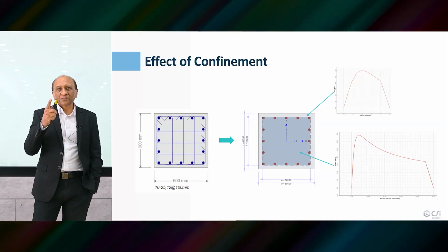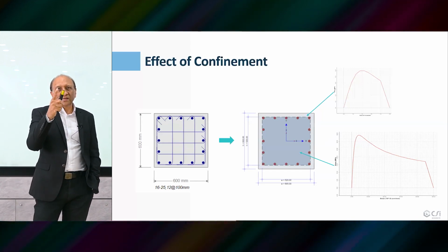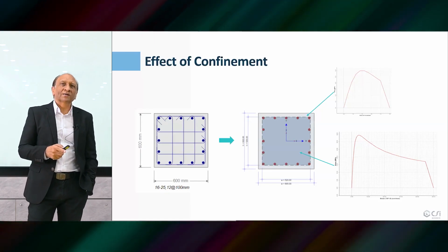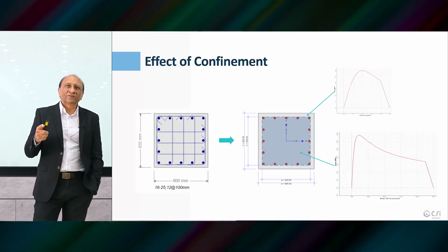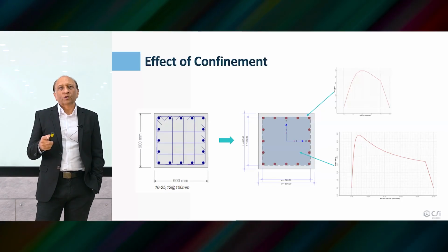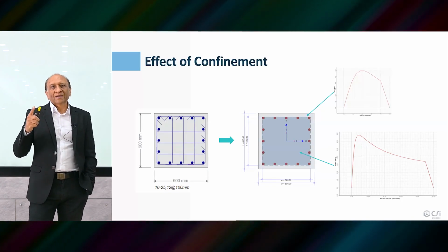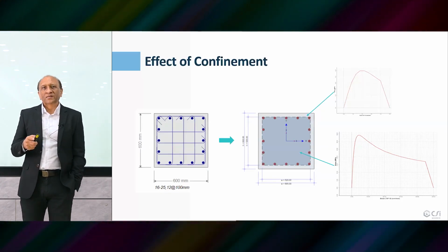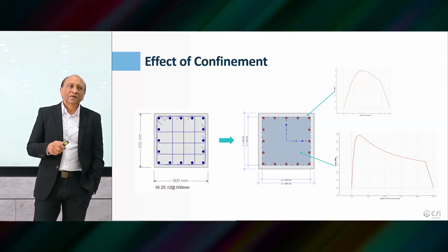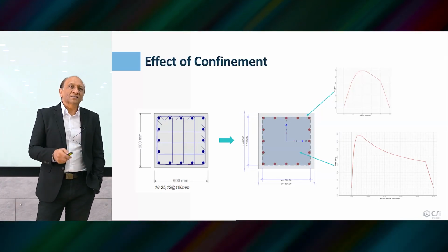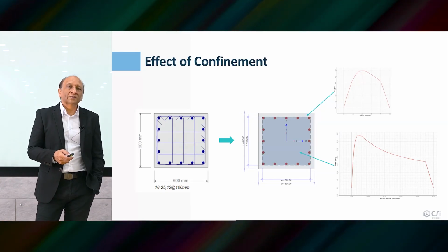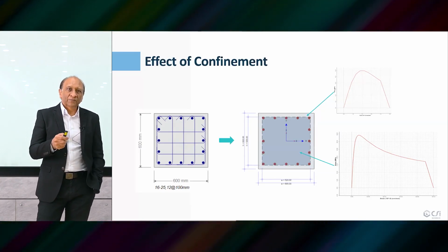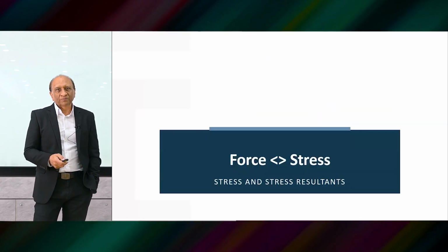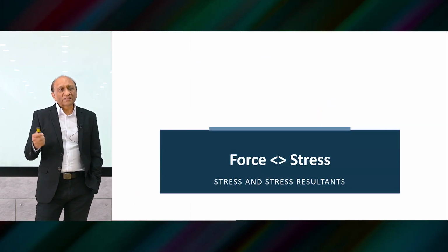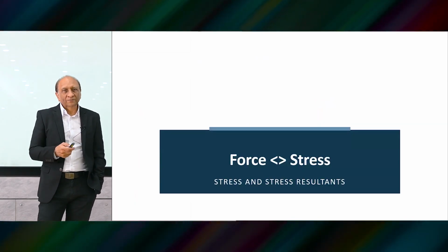In fact, they're not on the same scale. If you put them on the same scale, the unconfined has an extremely small strain capacity, 0.0035 or 0.004 or maybe 0.005 at most, and confined can go as high as 0.03 or 0.05 even. So you can see that we can drastically improve or alter the stress-strain relationship of concrete through confinement. So let's move on to the next one. We'll come back to these again.